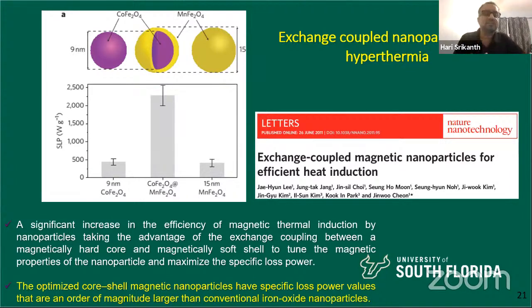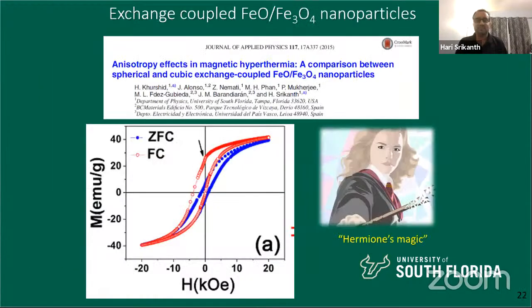However, I took one look at this, cobalt. Cobalt is poison. You can never use cobalt-based materials for medical treatment. So essentially, we need to look for iron oxide-based core shell approaches. And this is what we did. And I would like to credit my postdoc here. Her name is Hafsa Khurshid, and she's actually an assistant professor now in Sharjah in UAE. She's originally from Pakistan, but she was extremely clever in making chemically synthesized nanoparticles. And we call this Hafsa's magic or Hermione's magic.